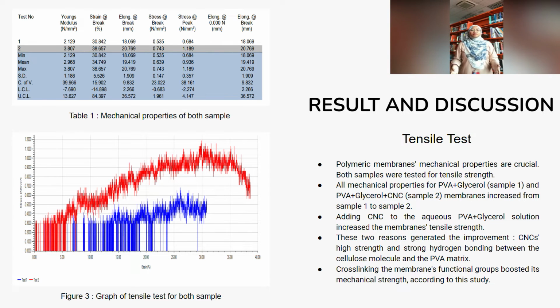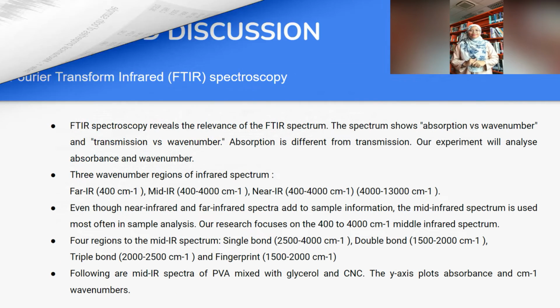The remarkable improvement in the mechanical properties of these composites was attributed to the CNC's intrinsic high strength and modulus, as well as a strong hydrogen bonding between the cellulose molecule and the PVA matrix. In other words, the improvement was caused by the combination of these two factors. According to the findings of the study, the mechanical strength of the membrane was significantly increased by the attaching of its functional groups to one another in a cross-linking pattern.